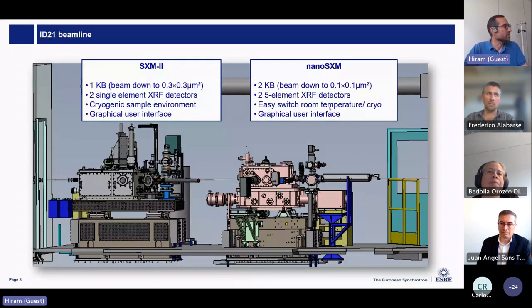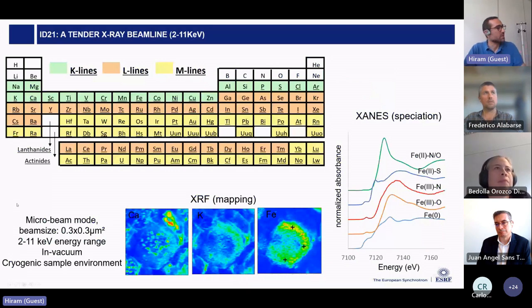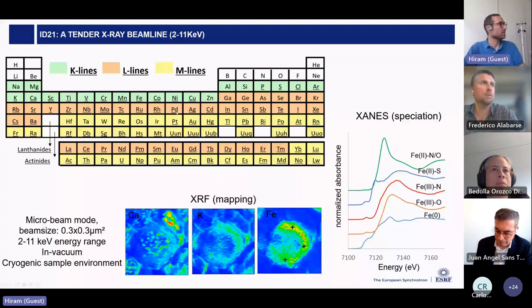So the beamline covers an energy range that goes from 2 to almost 11 kilo electron volts, which means that you can perform not only the mapping in X-ray fluorescence detection mode of elements, simultaneous detection, but also scans across the binding energies of the elements from phosphorus all the way to zinc now on these K edges, but also many of the L and even M edges, but obviously with less sensitivity. So we can analyze, either through mapping or a combination of mapping and X-ray absorption spectroscopy, many of the elements on the periodic table.